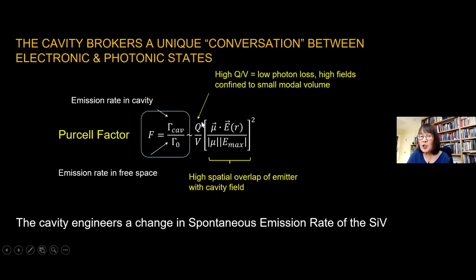This high Q over V, this is a quality factor. It describes the resonance of the cavity in frequency with the silicon vacancy. High Q over V means that I have a really high field, it's exquisitely in tune, and it's concentrated in a very small volume. This component is what I spoke about earlier in saying I need to pinpoint exactly where my silicon vacancy is, and be able to make sure that that field overlaps the position of that atomic scale entity.